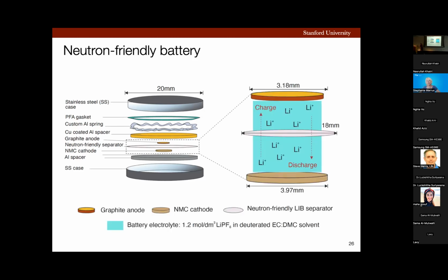Now, to revisit the electrodes, you can see that this T is the diameter, which is a neutron path length. So you can see from the Beer-Lambert law how making them small increases transmission from the battery. Now, here I would like to mention that a coin cell geometry is particularly advantageous for neutron tomography, because this geometry results in uniform attenuation throughout the scan, thus resulting in less imaging artifacts. In addition, these coin cells are pretty small, so you can stack a lot of them on top of each other for each neutron tomography scan. And they also reduce the use of expensive deuterated chemicals. So you can make a lot of coin cells with a very small volume of expensive chemical.